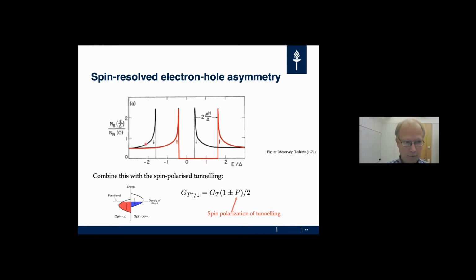The black picture, which is for the right spin, contains also an electron-hole asymmetric density of states, but with an opposite direction, such that the sum of these densities of states is actually completely symmetric with respect to zero. But now, if you combine this with spin polarized tunneling...